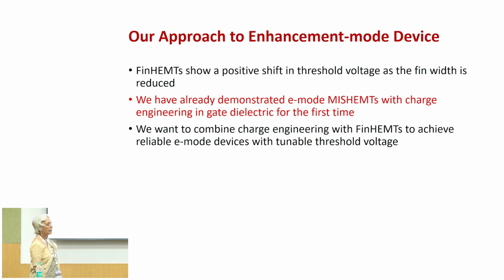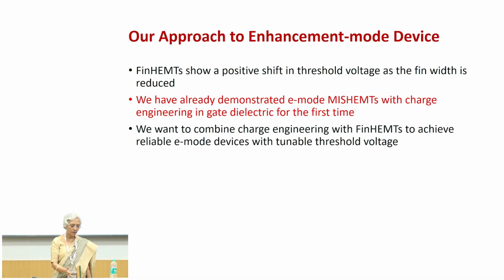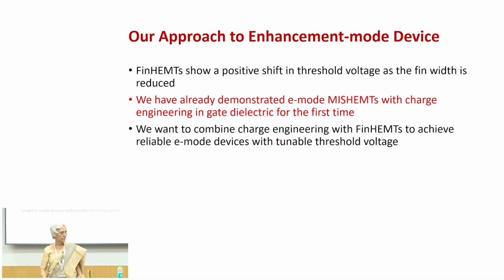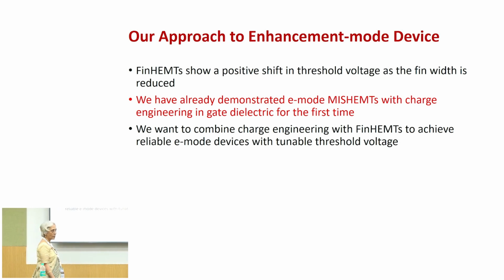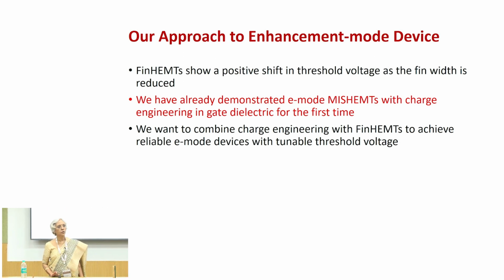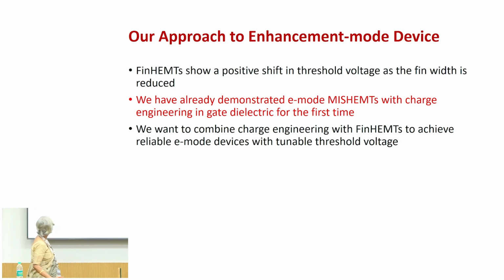Now, as I keep saying, in the fin HEMT or MIS HEMT, we have the side gates as well as the top gate, and these side gates can also deplete the channel charge. Therefore, in fin HEMTs there is always a shift in the threshold voltage which makes the threshold voltage less negative. So, we try to use this property of fin HEMT in order to realize an enhancement mode device, and the amount of the shift in the threshold voltage will depend on the fin geometry. So, we try to tweak the fin geometry and see how the threshold voltage is going to change.